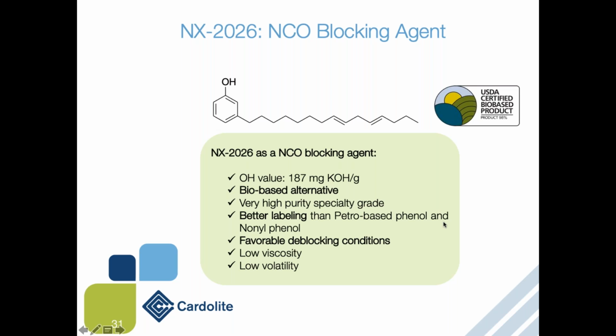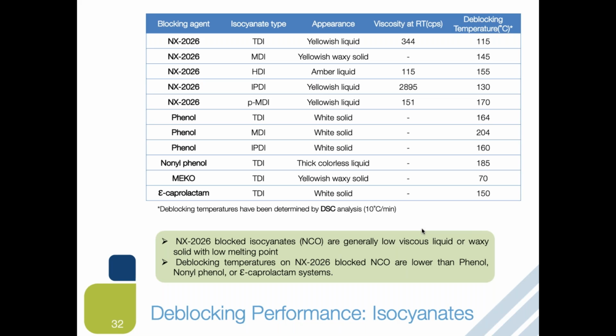And NX 2026 is also a product that has a low volatility, and also since this product being 100% bio-based, it offers better labeling than typically known petrol-based phenols and nonylphenol. And the next slide I'm going to go over, but NX 2026 has shown the favorable deblocking performances with a low viscosity. So this slide share the performance of NX 2026 in comparison to phenol, nonylphenol, MEKO, caprolactam with the various isocyanate.